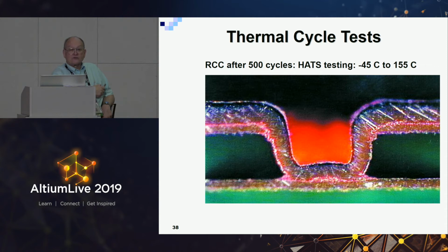The through holes will fail after 400 to 500 cycles. The micro via will go to 3,000. And in fact, a lot of times, companies send them back to me, and they said, we've gone 4,000 cycles, we're going to stop. We're not going to test to destruction like you wanted, because we don't know how long your boards are going to be on this machine, and we're losing money. So I said, okay, 4,000 is good enough. If it hasn't failed after 4,000 cycles, yeah, it's pretty robust.